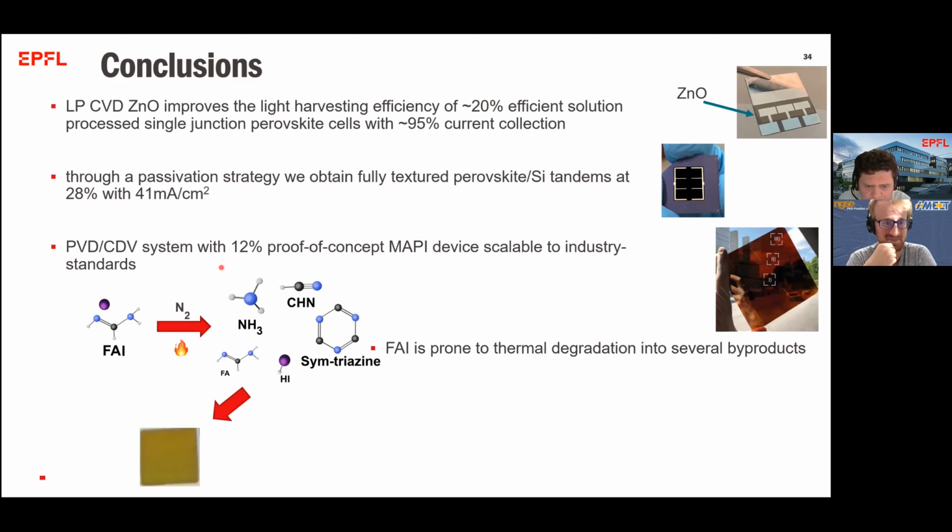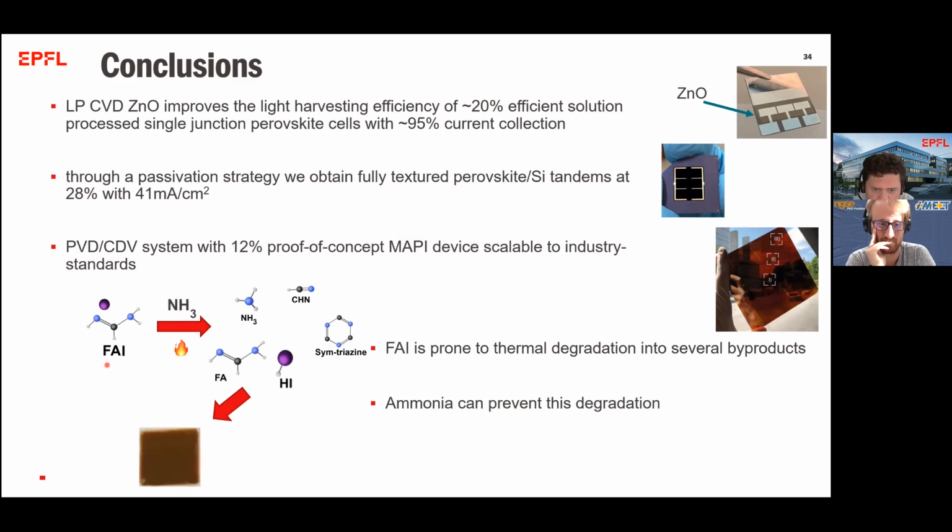iodide. And in the very last bit, I've shown you that formamidinium iodide, although it's probably a more stable organohalide per se, under the conditions where we use to deposit it, it decomposes in a big zoo of chemicals. And by changing the amount of chemicals in the system, you can in fact still get a formamidinium lead iodide perovskite, but this is still ongoing work.